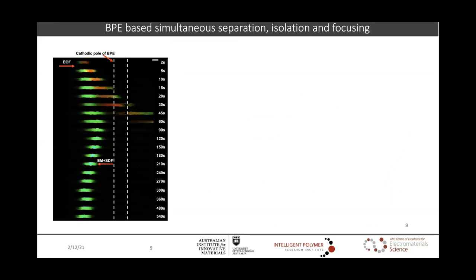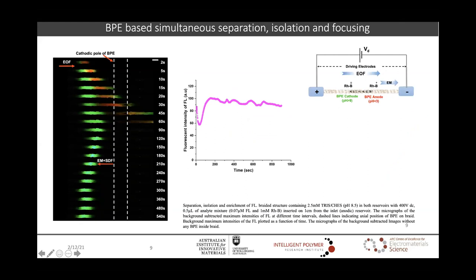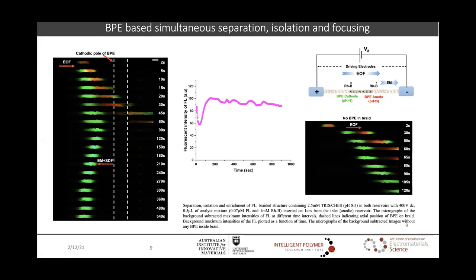In the last, we demonstrated the simultaneous separation, isolation, and focusing on this open integrated system. And here you can see that we were able to separate and isolate anionic fluorescein from a complex mixture of the cationic rhodamine B and complex electrolyte system, with its concentration enrichment and intensity stable over time. However, when there was no BPE in the system, the charged analytes do separate on the basis of their electrophoretic mobilities, but there was no isolation or concentration enrichment.